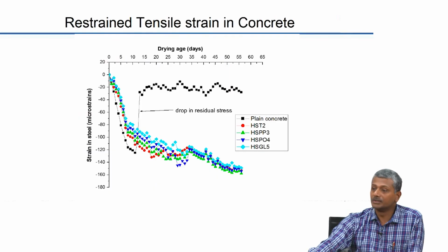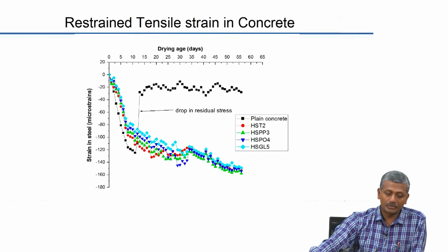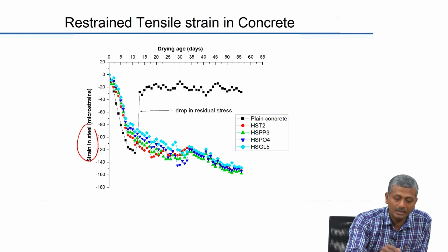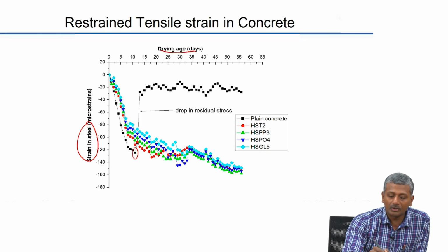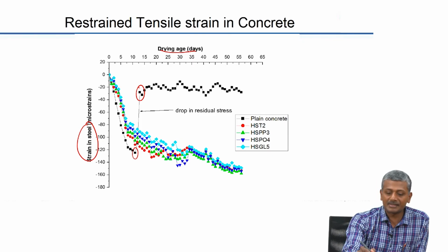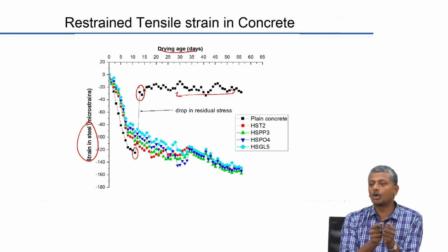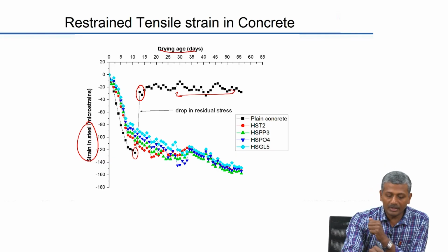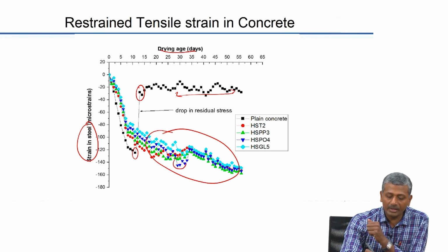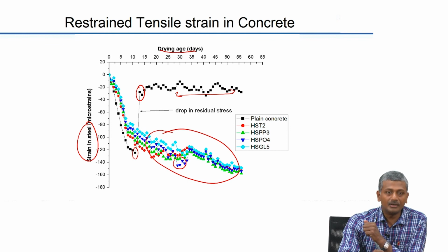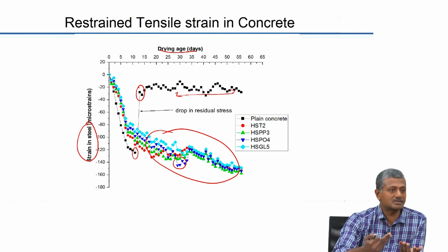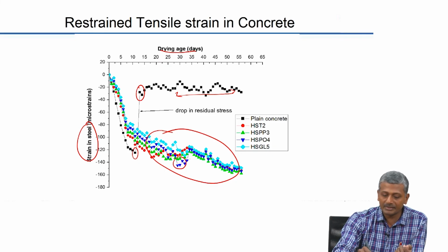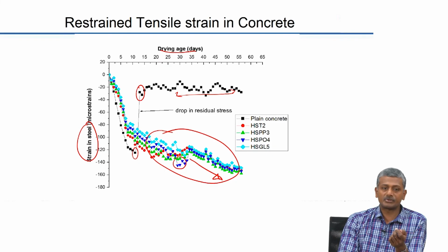This is just showing you the residual stress, or rather sorry, this is the strain in steel versus the drying age. For the control concrete, as soon as the crack appears, you have a major reduction. There is some level of residual strain which is built up because of the interlock between the aggregates. But in all the other systems, you may see some small kinks at which there is a drop in strain, but as soon as the stress gets transferred after cracking to the steel fibers or to the polymeric fibers, there is again a build up of your residual stress in the system.